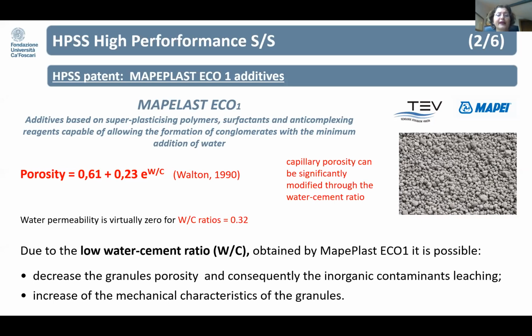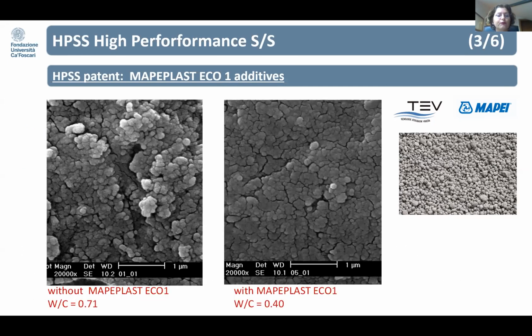In addition, the heavy metals are not only physically stabilized, but also chemically stabilized, meaning their precipitation is in much less soluble species, therefore in a metal hydroxide in relation to the high level of pH given by the cement. Those two images show the difference in the matrix with or without the additive, and the relative water and cement ratio that can be obtained using the additive, that goes from 0.71 without the additives to 0.40 with the additives.